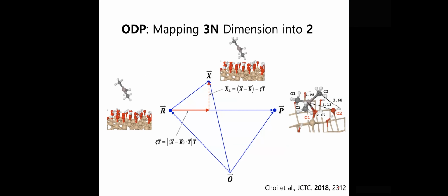So by using these two vectors, you can do two-dimensional umbrella sampling. That is exactly what we did. This is a bit complicated, but this is the overall structure of what we actually did. Initially, you need some small set of quantum data. Otherwise, you have nothing, right? So using those data, you can train machine learning, and Deep MD gives you initial MD parameters, which are not good, but still you have something.